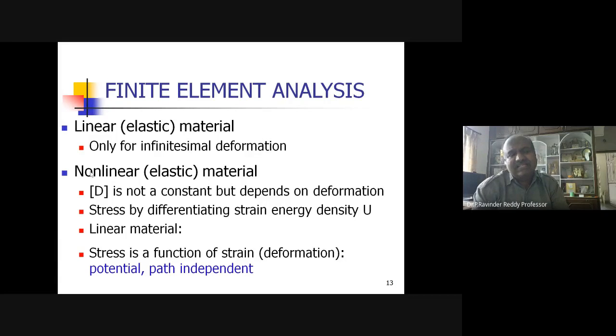And the other is nonlinear material, nonlinear geometry also. Nonlinear material, because we are saying the chip is flowing. If it is brittle, linear is enough. When the chips are in contact, then there is going to be deformation while machining. Then we need to have the nonlinear material models. So here, generally, D is the material matrix. So this D is no more constant. It depends on either the deformation or the temperature.